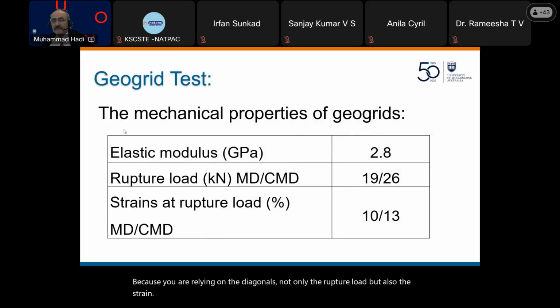We did some physical tests, and the elastic modulus is about 2.8 gigapascals. The rupture load, 19 and 26 for the machine and cross machine direction respectively, and the strains, 10 and 13, machine and cross machine respectively.